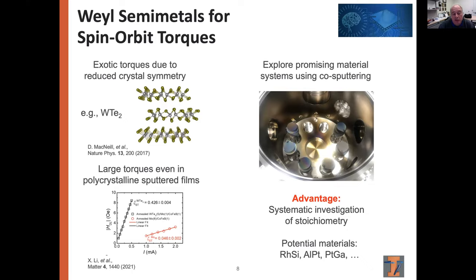So our group is already exploring the use of Weyl semi-metals for spin-orbit torques. There are certain key interesting ideas about using Weyl semi-metals. One is that the electronic properties are typically derived from the rather low crystal symmetries of these materials. And these low crystal symmetries also relax some of the restrictions that you typically have for spin-orbit torques. So it allows us to generate spin-orbit torques with symmetries that you don't find in conventional materials. And this is especially interesting because a big problem in magnetic switching is switching magnetic materials that have magnetizations that are perpendicular to the layered structures where they're used. And Weyl semi-metals have something very attractive to offer there because they specifically generate torques that allow you to do this.